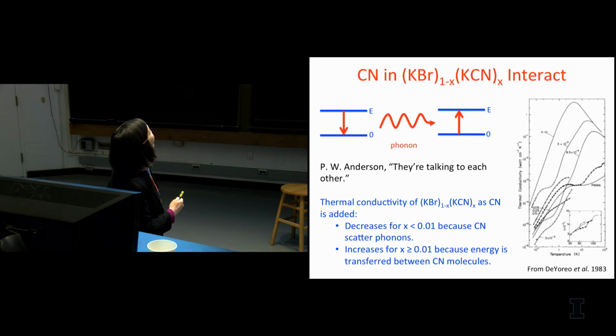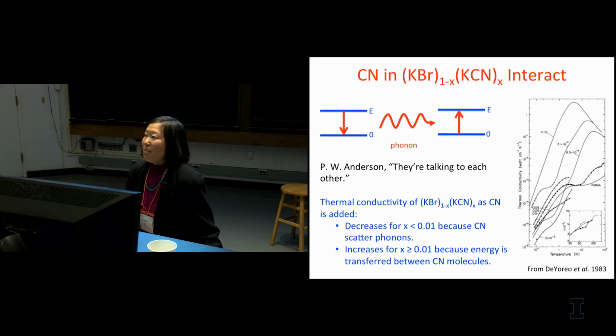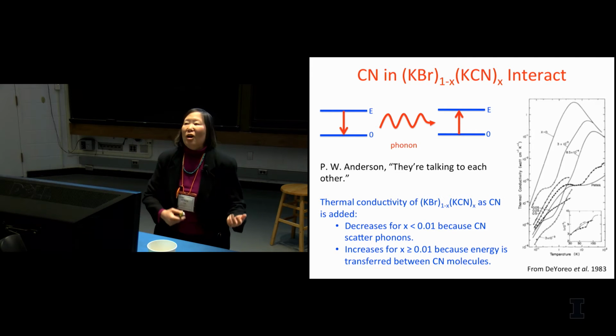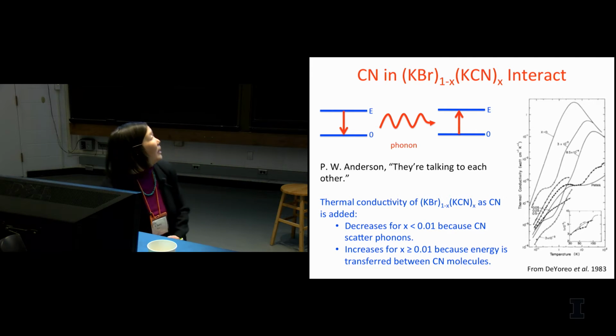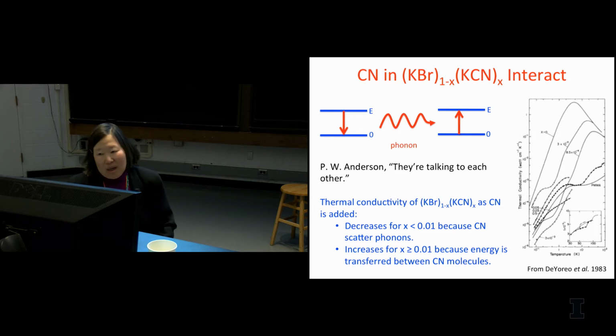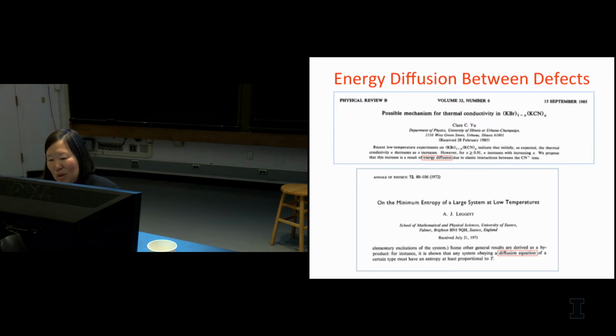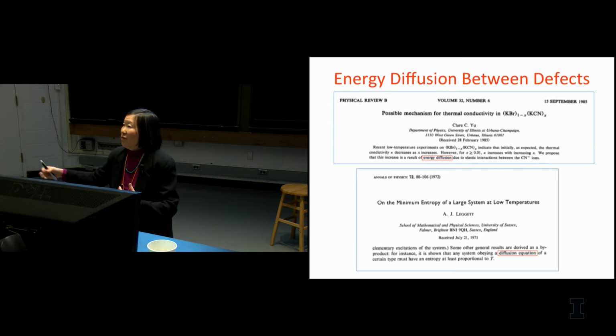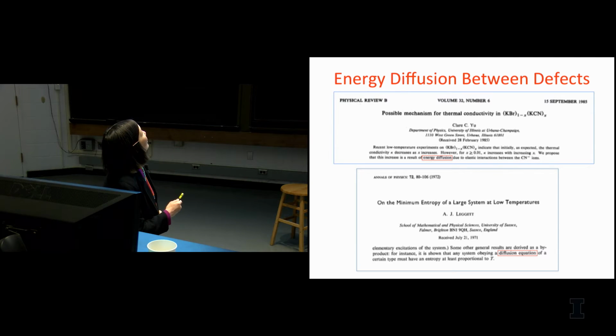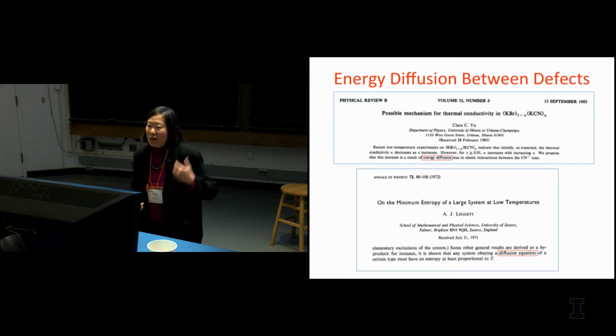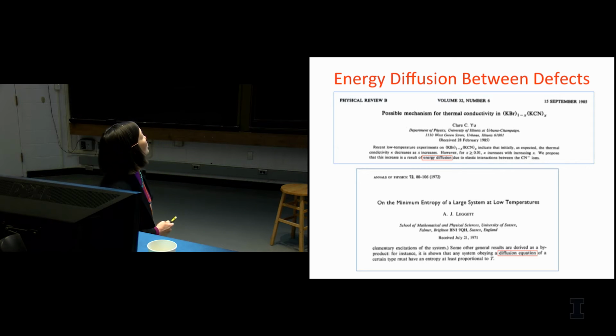By that he meant that with the cyanides, the energy in one cyanide de-excites, emits a phonon that's absorbed by another cyanide. And as they pass energy like a bucket brigade, you've got another channel for conducting heat. So you've basically got this new mechanism for energy diffusion. And I wrote a paper based on that idea of energy diffusion among the cyanide ions. I did ask Phil if he wanted to be a co-author. He declined.